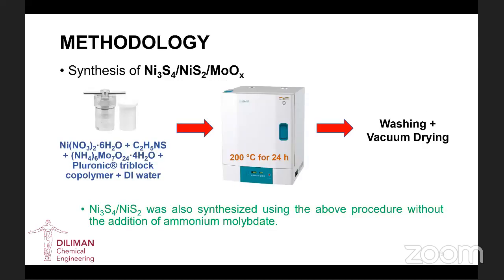So for the methodology, nickel nitrate hexahydrate, thioacetamide, and ammonium molybdate and pluronic triblock copolymer was added to DI water and placed in Teflon-lined autoclave.